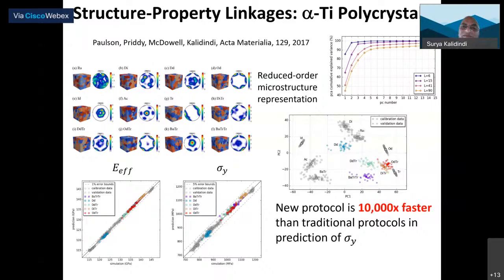People generally use pole figures to see the texture, but that's what we call one-point statistics. Two-point statistics actually captures information like grain size distribution, grain neighborhood, and all that information is in the two-point statistics. The feature engineering is exactly the same, and then it can make predictions for effective properties, modulus and yield strength.